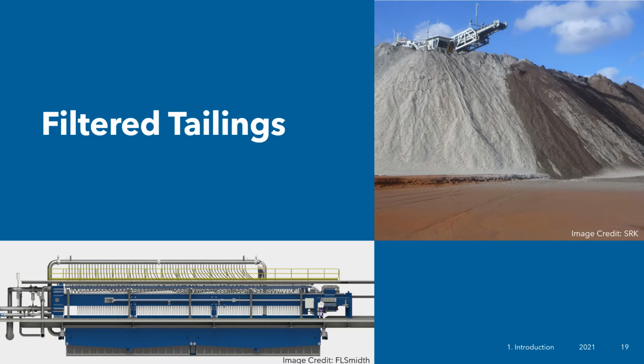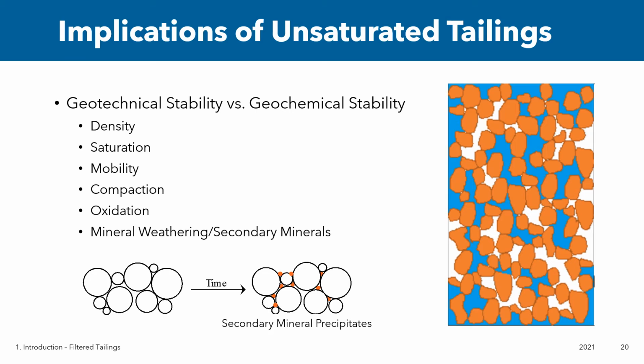Having tailings at their optimum water content means that the particles fit together in the densest arrangement without being too stiff, which is important for physical strength, but it also means that the tailings are unsaturated. Since the tailings must be unsaturated to achieve maximum geotechnical stability, the pore space is filled with both oxygen and water. As previously mentioned, those sulfides, oxygen, and water are the three components that can cause acidic drainage, so there is a major potential for geochemical instability in this configuration.